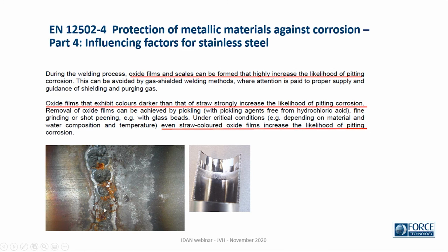And of course, if we don't have any protection at all, we will both have oxidation and would have heat tint also very much above the straw. And you can see corrosion has started. Again, it's just a humid domestic water application. But this is, on the other hand, a perfect weld in an electropolished tube for pure water and a pharmaceutical plant. Full protection with purge gas and a TIG process, which is probably automatic as it looks like this. And we can not see any. The yellow here is reflections. It's in fact fully bright.